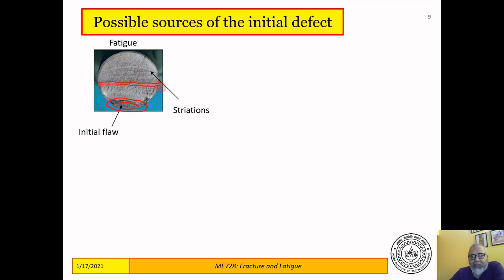So this took place over a very long period of time, and then led to a crack which then grew probably catastrophically and led to failure of the shaft. So fatigue is one major source. Fatigue, or long operations over cyclic loading, is one of the major sources of the initial defects that ultimately lead to failure of structures. The second major source is aggressive environments.